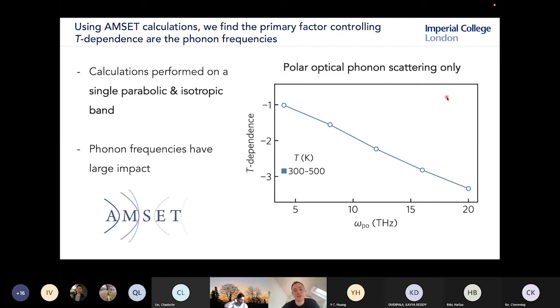And what I found was that a single materials parameter, namely the polar phonon frequency, by changing that, you can actually tune the temperature dependence across a really broad range. So if you have a small polar phonon frequency, you get a temperature dependence of -1. And as you increase that, you get a temperature dependence over -3. And these results were at low temperature. But when you go to high temperature, you see, again, quite a large modulation, although it is reduced somewhat. So the phonon frequencies have a large impact.